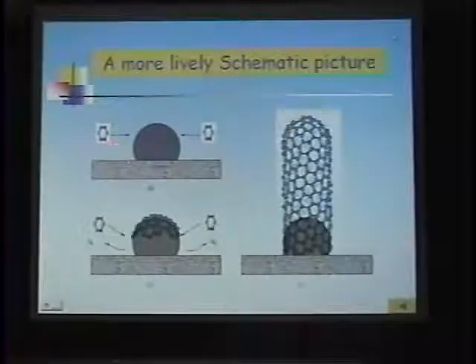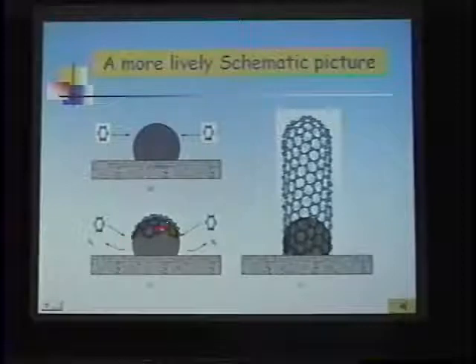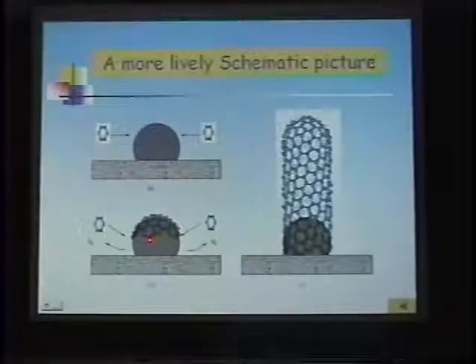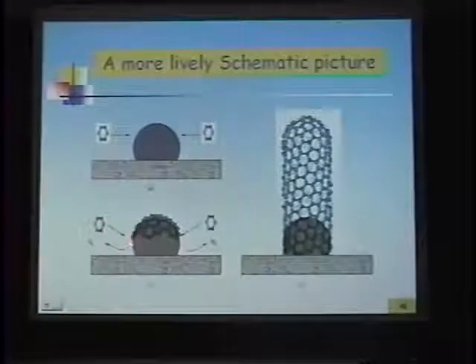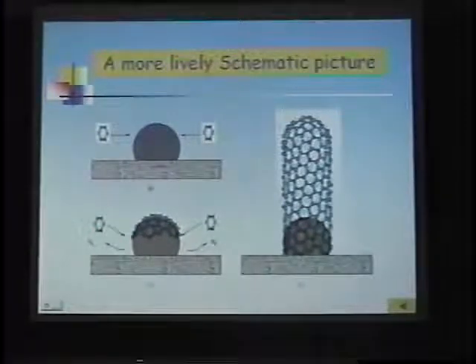First, the benzene molecule will be absorbed on the catalyst surface. Then, dissociation of hydrogen occurs and the hydrogen will be released, and the carbon-6 ring will aggregate to a graphene sheet, and then precipitate to tubular seeds. The further incorporation of benzene molecules at the edge will result in the growth of carbon nanotubes. This is the story about the growth mechanism.